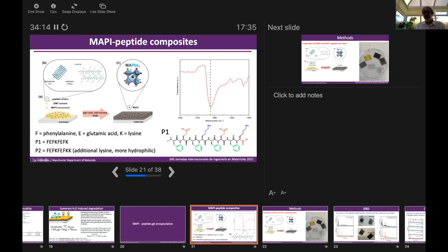When these things are put together, essentially what happens is the phenylalanine comes together and forms this hydrophobic core. These then organize into beta sheets, which then get entangled and form a network gel material, which can be swollen by immersion in water, just like any other gel, and then subsequently dried out. And the beta sheet formation in water is indicated by an absorption peak in FTIR at about 1630 wave numbers.